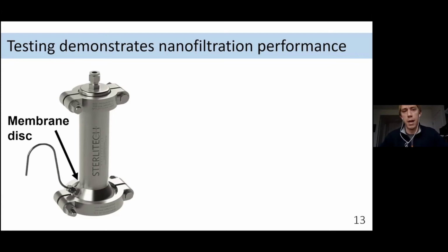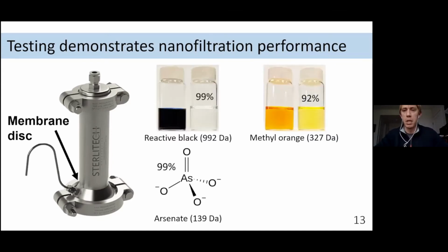Pressure is applied in dead-end configuration via compressed gas, and we're able to squeeze the water or other organic solution through the membrane and out through that spout where we can analyze it in real time. A couple of different experiments we've performed: we've done a lot of work with organic dye molecules in aqueous solutions. These are really easy to characterize and also monodisperse in terms of their hydrodynamic radius, for instance.